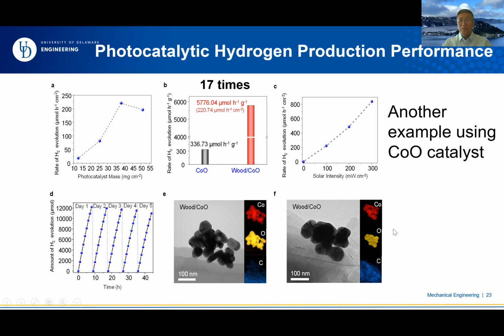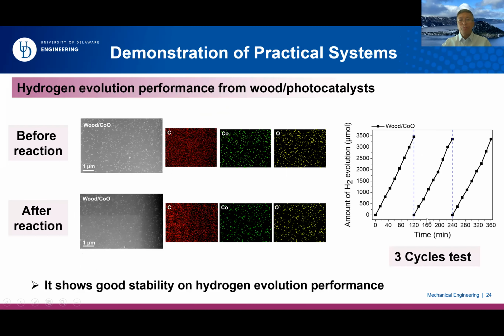And here we also test, for example, before and after the reaction, and you can see the morphology and the particle size of the catalyst doesn't change much. So that again demonstrates the stability of this catalyst or the strategy. And here again, to show that before and after reaction, the elemental signal distribution on the wood structure doesn't change much as well. That gives you direct evidence to show the good stability of this approach.